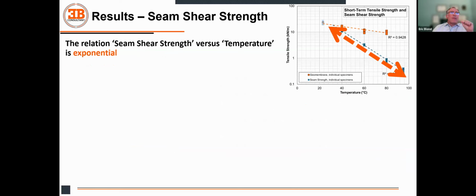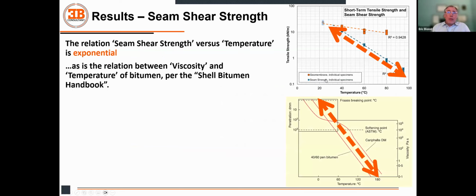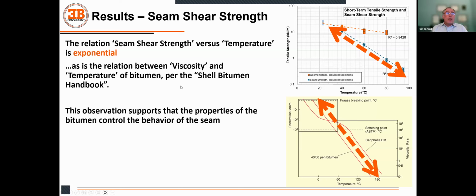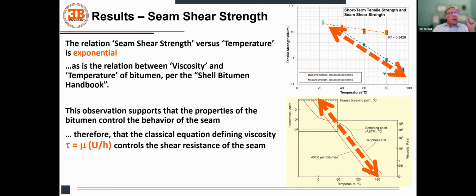And what we found is, in fact, the relation between the seam shear strength versus the temperature is exponential, as you can see here. When we plot the numbers in a log linear scale, you can see a straight line. So that means there is a logarithmic relation connecting the two. And we realized that it's exactly the same shape of behavior as the relation connecting viscosity and temperature per the Shell Bitumen Handbook. So this observation, just looking at the shape of the curves, really supports that the properties of the bitumen are controlling the behavior of the seam, and therefore that the classical equation connecting viscosity with other parameters is in fact controlling the shear strength of the seam.